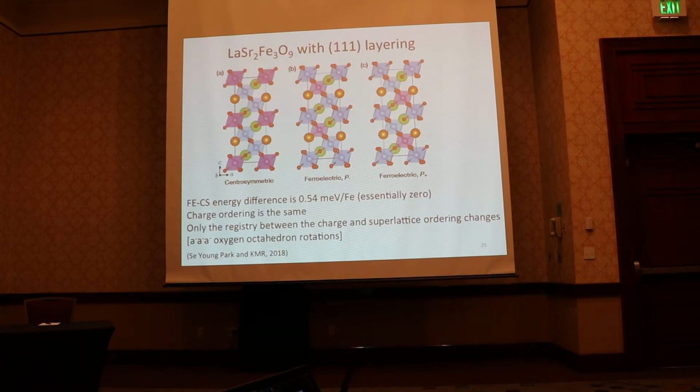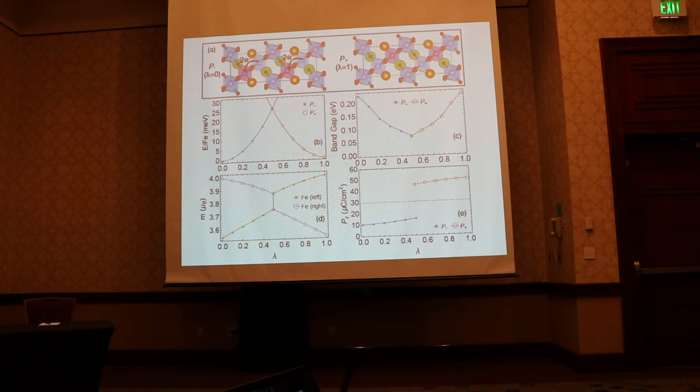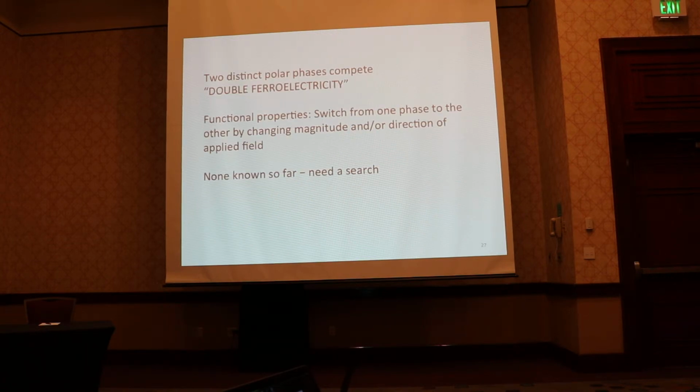I've given lots of talks about this, about the Vandenberg superlattices, and Se Young and I also have recently put out a paper where we have charge ordered ferroelectricity in 111 layered lanthanum strontium iron oxide. There's a big jump in the polarization, and the band gap does not go to zero, although it's very small. Okay, so here's my last slide.